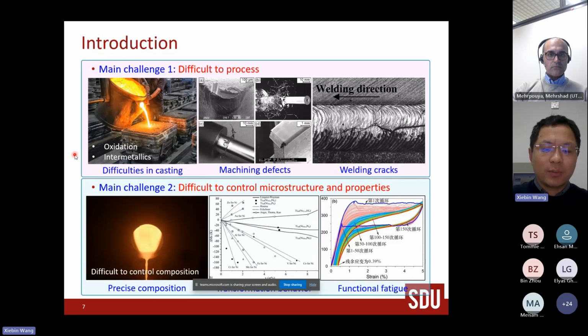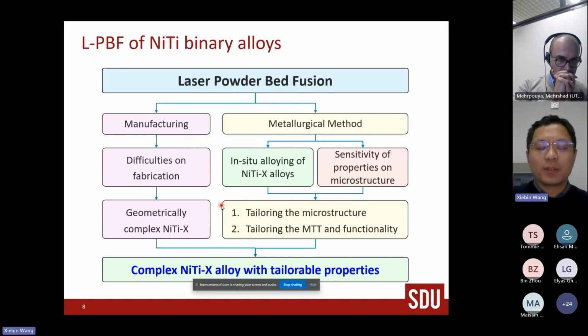It is well known that the transformation behavior of nickel titanium alloys is very sensitive to its composition. For example, for nickel-rich alloys, if you add 0.1% of nickel, the transformation temperature will decrease by around 20 degrees. And also, when you add ternary elements, the transformation temperatures will change a lot. It depends highly on the type of elements and the amount of the elements. And also, for the nickel titanium based alloys or other shape memory alloys, we all suffer from functional degradation.